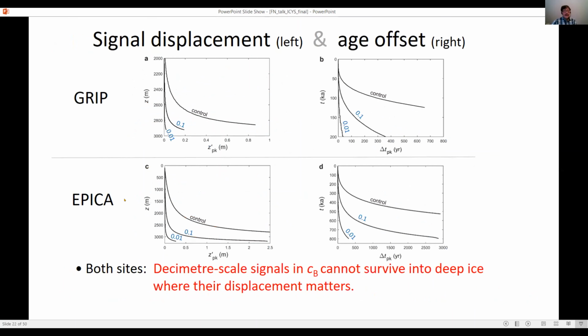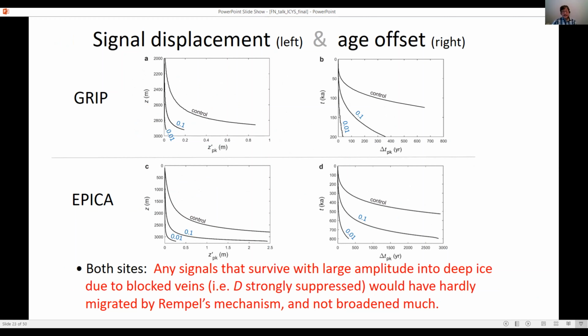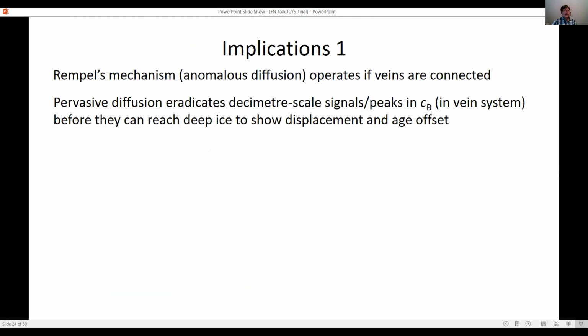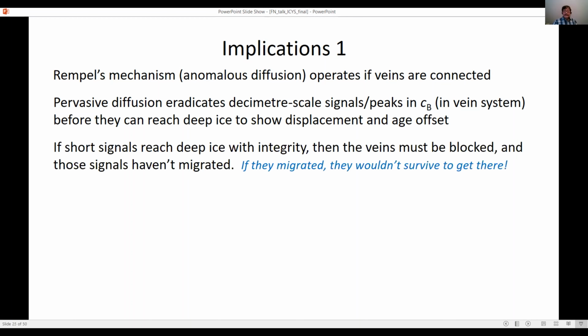For completeness, I show the EPICA signal displacements and age offsets as well. Conclusions are identical. Short scale signals can't survive in the deep ice where their displacements matter paleoclimatically. On the other hand, if they do get there because the veins are blocked, they would hardly have migrated. So these are the results really. Rempel's mechanism operates if the veins are connected, except that there is a strong diffusion that eradicates the amplitude before they can reach deep ice to show that age offset. If they do get there, because the veins are blocked, they haven't migrated. If they migrated, they wouldn't have survived the diffusion to get there in the first place.